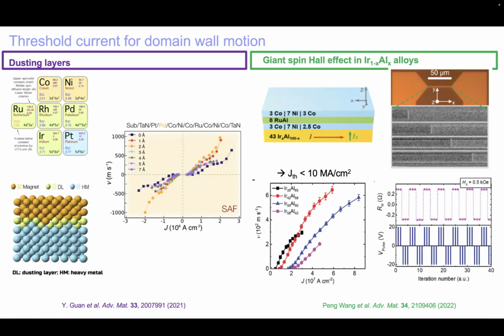Turns out the interfaces are key to everything here. And by manipulating the interfaces, even by the introduction of a few sub-monolayers of certain metals, we can change this threshold current, for example. We can reduce it by a factor of 10. It turns out this was important.